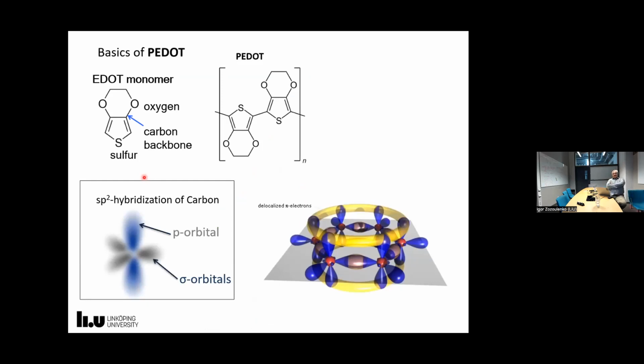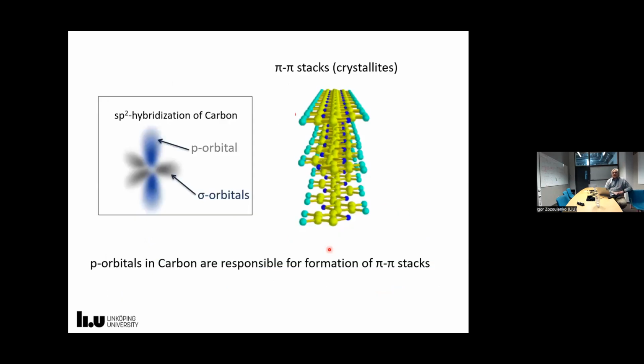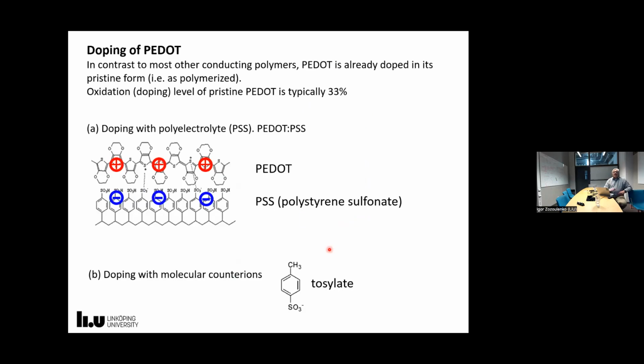Okay, so this is the chemical structure of PEDOT. What is important here is this bond. So this is a carbon-carbon bond, and it's composed of carbon atoms in sp2 hybridization. It means you have sigma orbitals, which create strong covalent bonds, but the p orbitals are situated in the vertical direction, and these p orbitals provide delocalized pi electrons. These electrons are responsible for the electronic properties of this material and the formation of pi stacks. So this is an example of van der Waals bonding due to these bonds. Okay, it's very important that PEDOT in